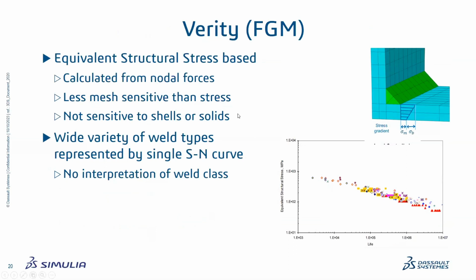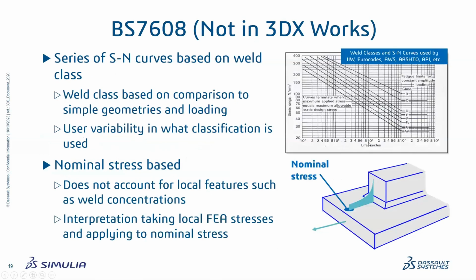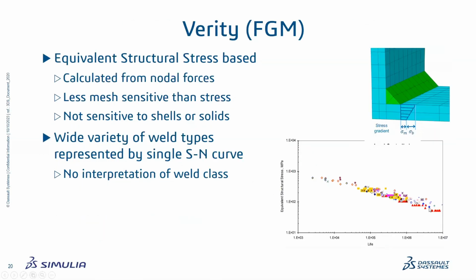And that's why generally in 3DEXPERIENCE, we've put in the Verity approach. This changes things up in the background, but like we saw from the example, you don't necessarily need to worry about this. The main thing it brings out is that because it's looking at this structural stress, which is based upon the forces across the cross-section of the attachments, that tends to collapse all of these different curves that we saw here into a single curve. And so that's why we no longer need to interpret things for Verity. We can just say it's a steel weld or it's an aluminium weld, and we just have a single curve here, and then we can go ahead and do that.